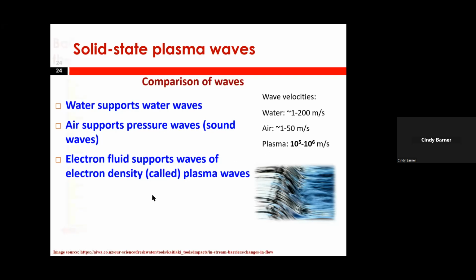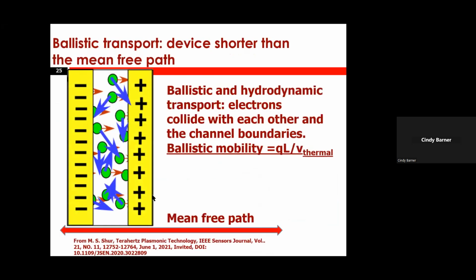And now let's look at what happens in a very short device that is much smaller than the mean free path. So this is the mean free path, and this is the dimension of the device. With this velocity, the thermal or Fermi velocity, which is on the order of 10 to the 5th meters per second or larger, the electron spends very little time inside the device and hits the contacts.